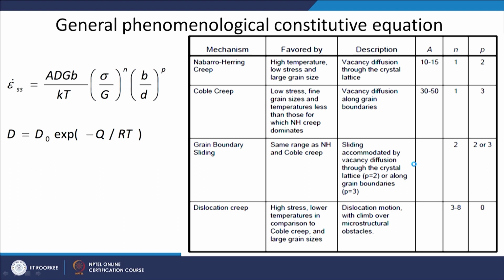So in fact I can summarize this in a nutshell here. Instead of giving you different creep equations, I am giving you a generalized creep equation, where epsilon dot is related to diffusion coefficient, shear modulus, Burgers vector, temperature, and stress normalized with shear modulus with an exponent n, and grain size normalized with the Burgers vector with an exponent p. So p is your grain size exponent and n is your stress exponent, and of course D is D0 exponential minus Q by RT.